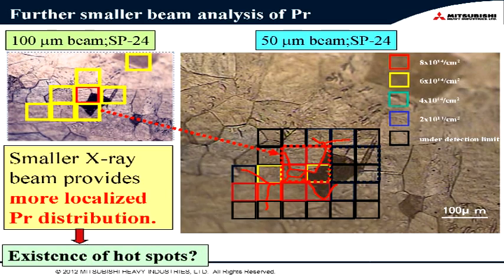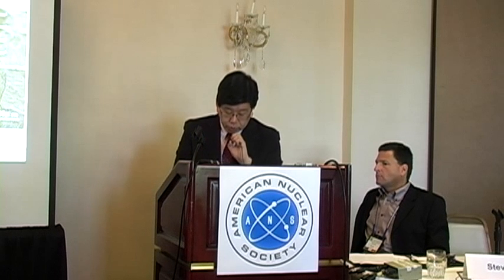And if we use a further smaller beam analysis, we analyze this very large praseodymium region with a smaller X-ray beam. And we also detected a more localized praseodymium distribution. So it might suggest the existence of hotspots for transmutation, maybe.